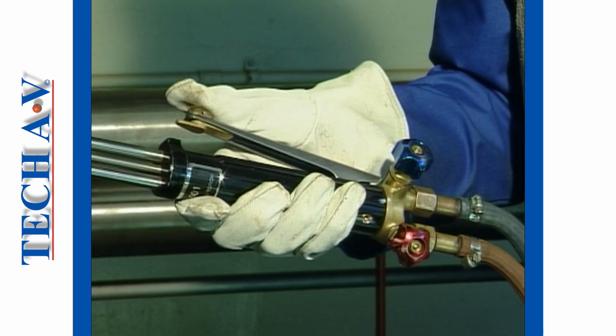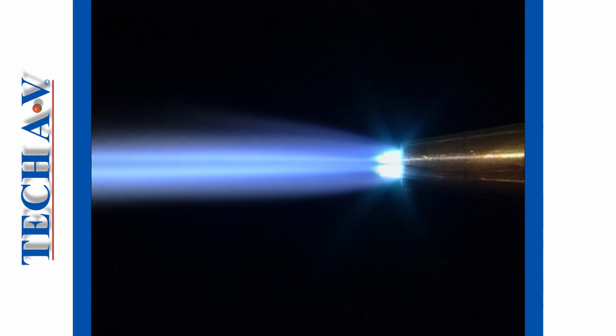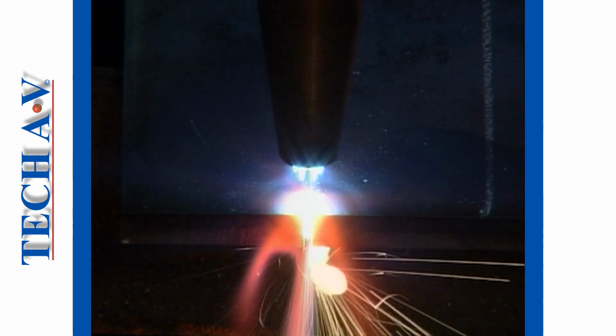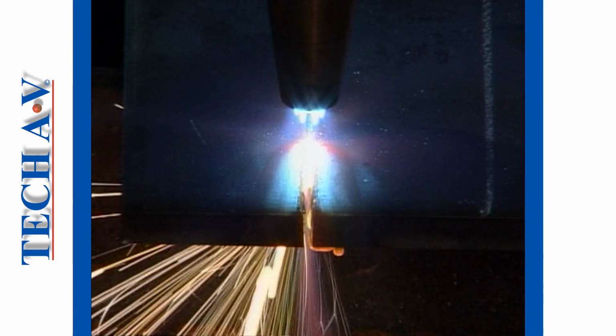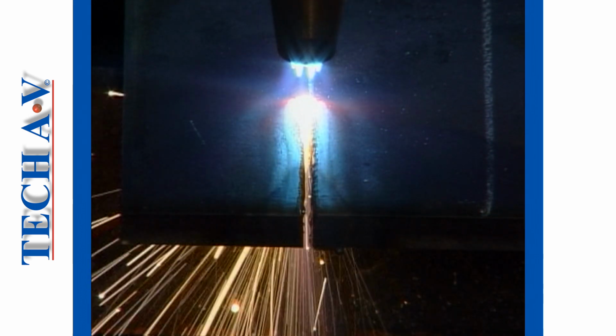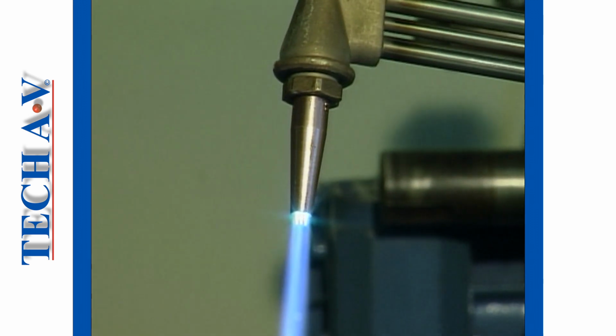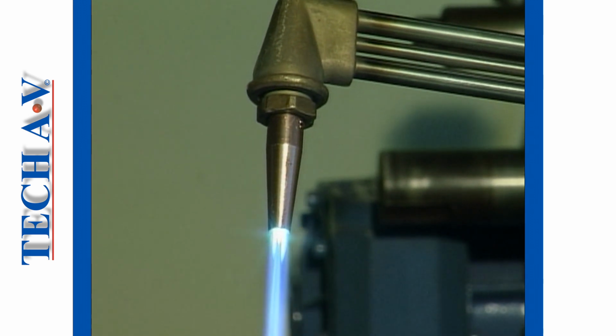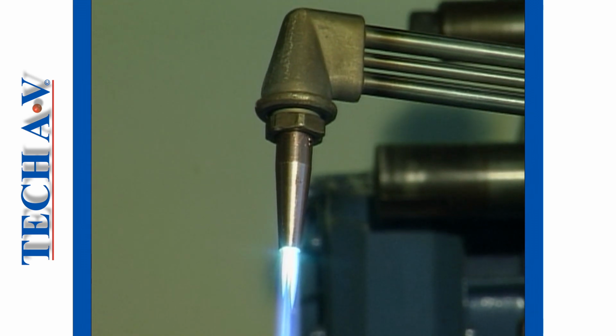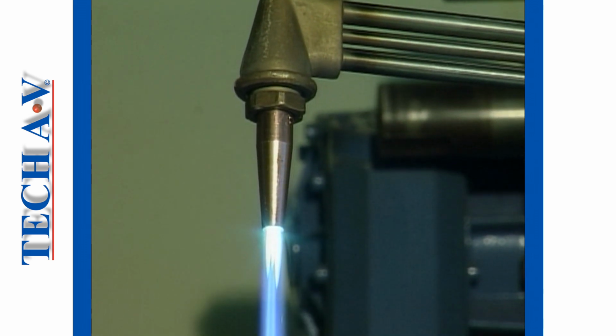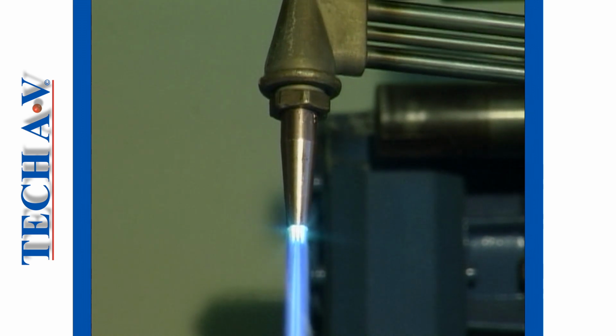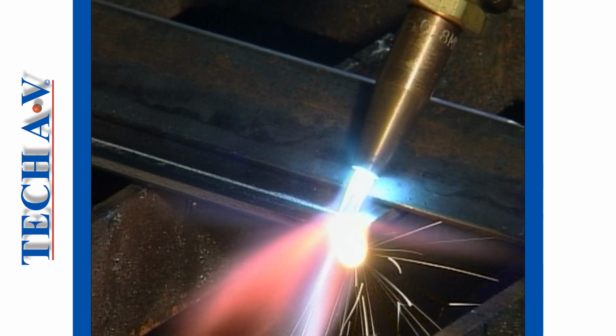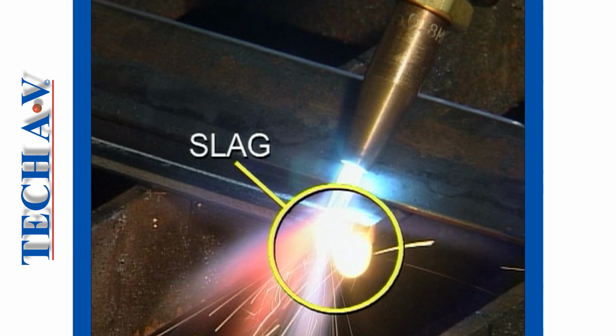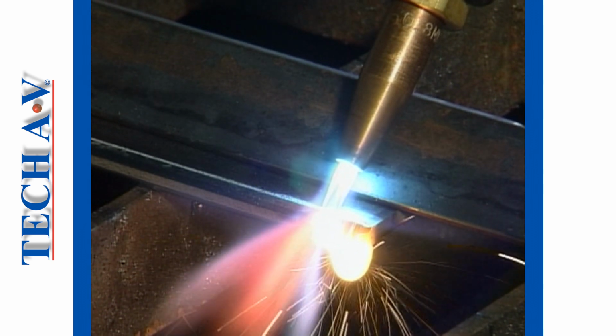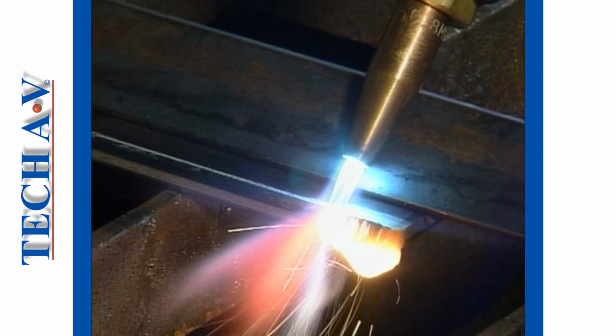Press down on the cutting lever and observe the preheat flames, which should remain neutral. With a properly prepared torch, you can expect to achieve a neat, clean cut. However, if the preheating flames tend to carburize when the cutting lever is depressed, then open up the oxygen control valve a little more. A carburizing flame will cause excessive slag formation, and a very rough cut will be created.